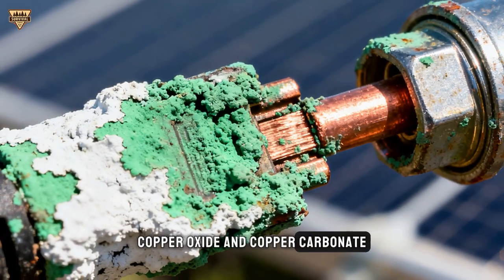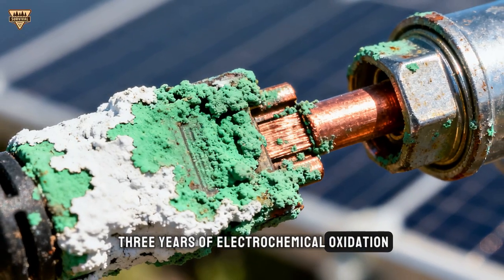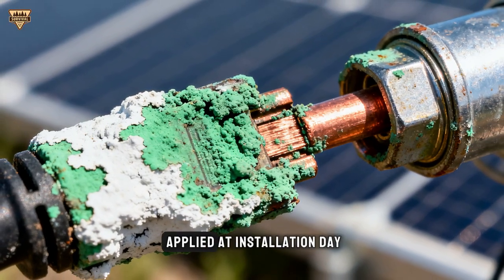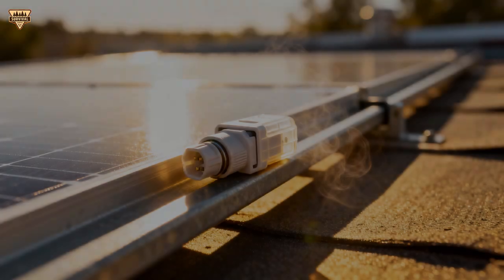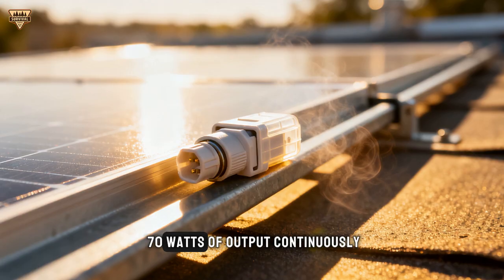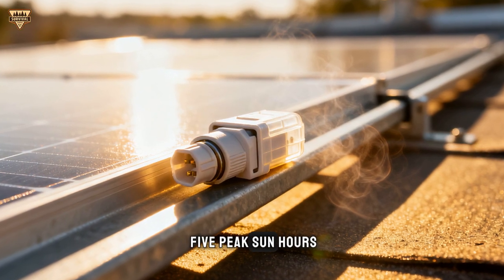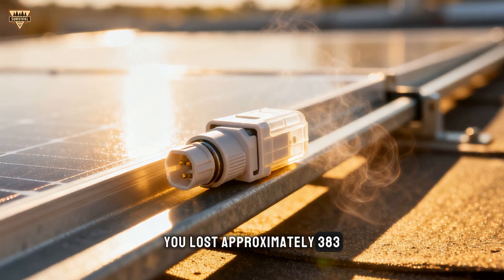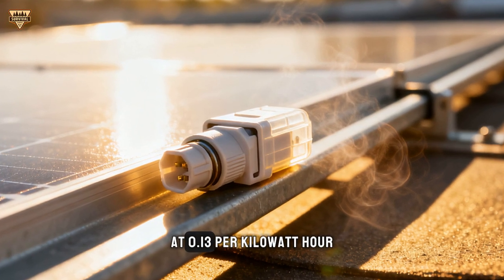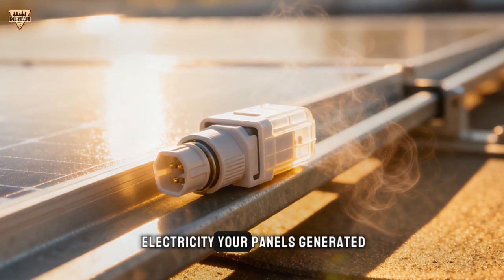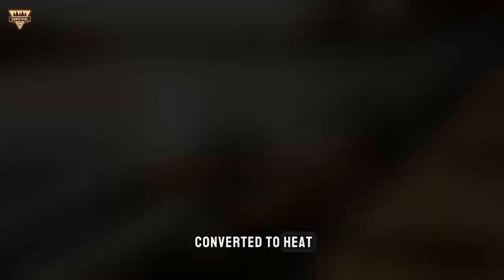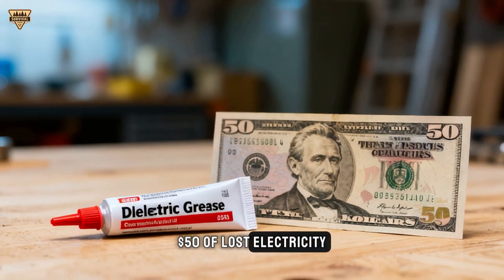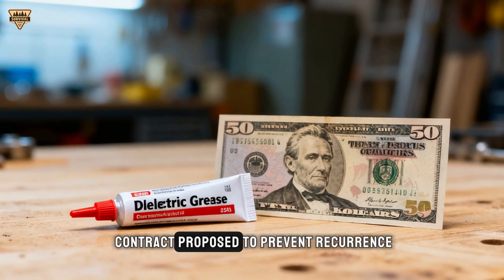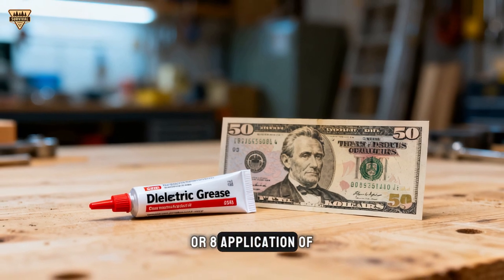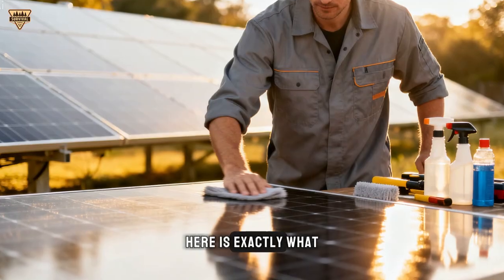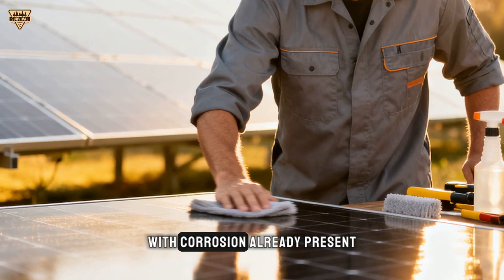Copper oxide and copper carbonate: the visible evidence of 3 years of electrochemical oxidation that $0.08 of dielectric grease applied at installation day would have prevented entirely. The output you lost over 3 years: if your system lost 70 watts of output continuously over 3 years of 5 peak sun hours per day, you lost approximately 383 kilowatt hours of electricity generation. At $0.13 per kilowatt hour, that is $50 of electricity your panels generated, and your corroded connectors converted to heat instead of delivering to your battery. $50 of lost electricity. A $220 annual maintenance contract proposed to prevent recurrence, and $0.08 application of dielectric grease that prevents it permanently. Here is exactly what to do for both new installations and existing systems with corrosion already present.